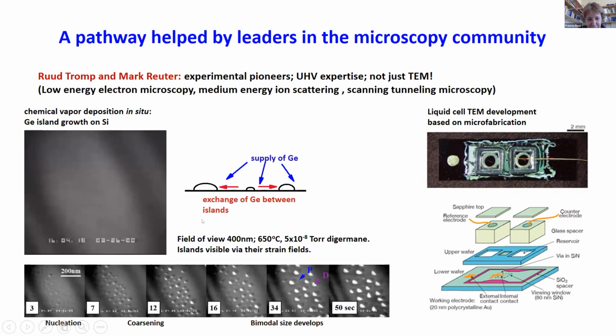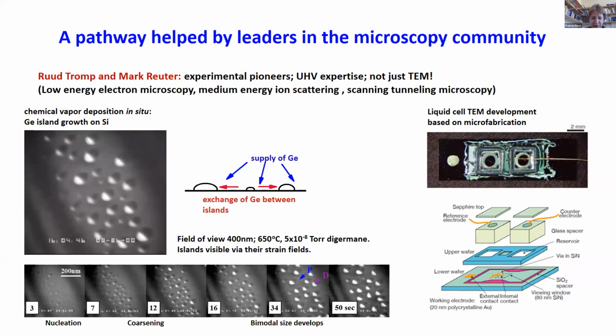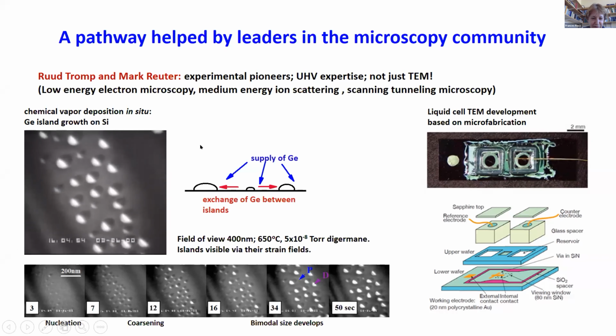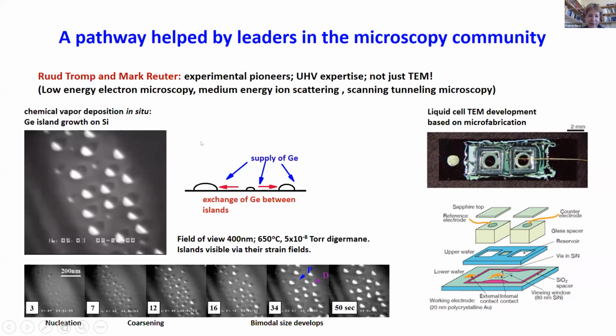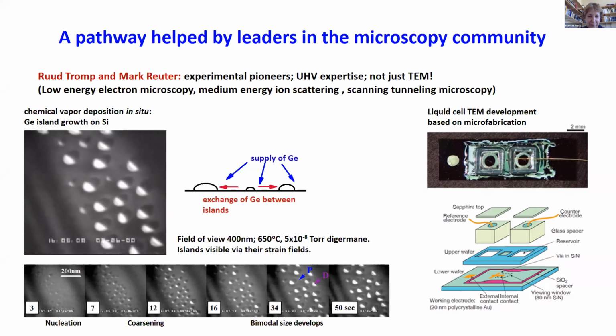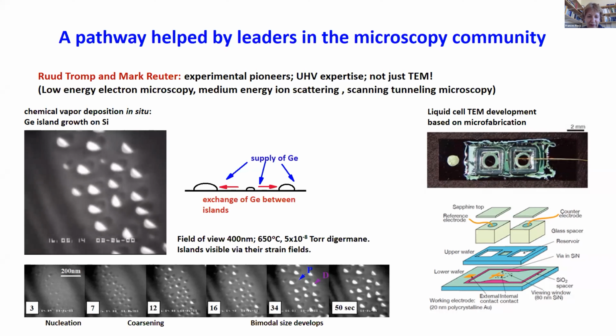So this movie shows germanium quantum dots spontaneously forming on a silicon surface. They're showing up because of their strain contrast. And if you look at the small ones, you see that the little ones disappear and the big ones keep growing. And this is while we're still adding flux. So the small ones are shrinking even though the flux continues to flow during the experiment.